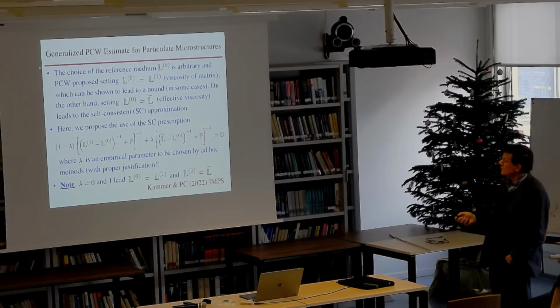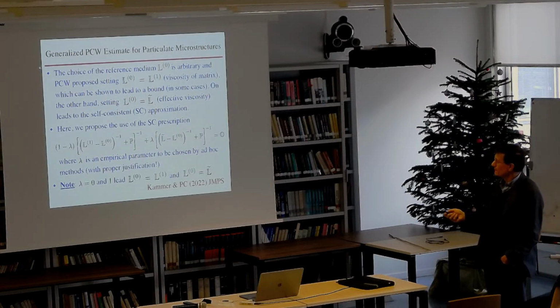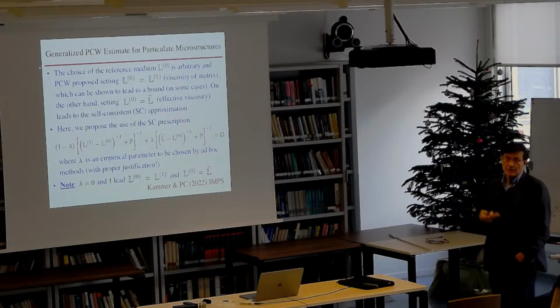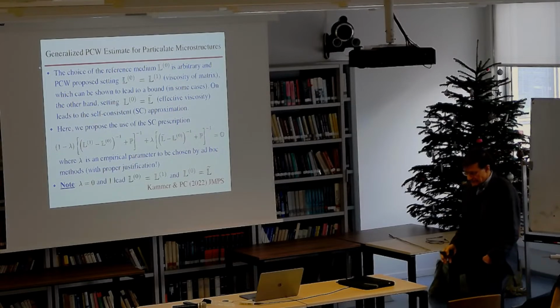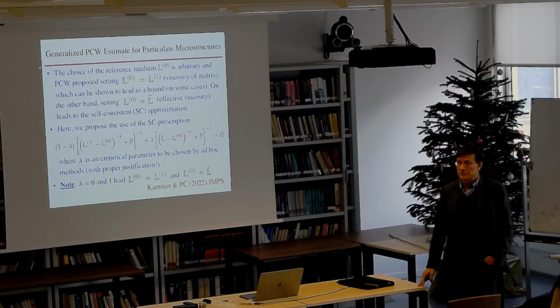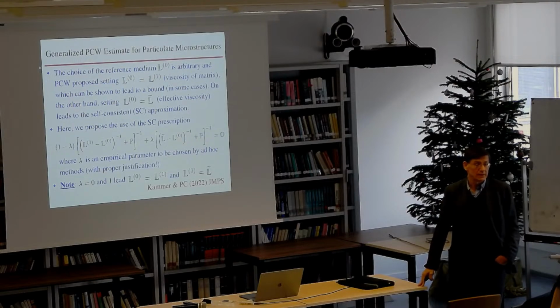So if you choose the L0, this reference medium in the homogeneous reference medium for the Hashin-Shtrikman estimates, and you set it equal to L tilde, the effective viscosity tensor of the composite, which you don't know, you generate an implicit equation for this L tilde, right? And you can solve that equation, and it turns out to be the same equation as the self-consistent method.